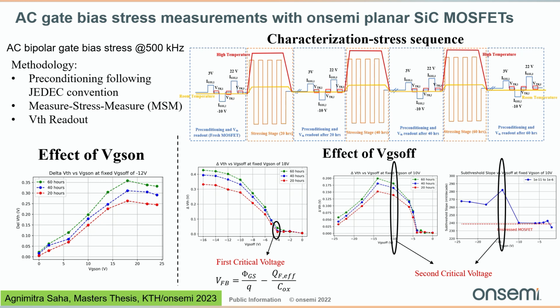And here Agnimitra looked into the dependence of different Vgs on voltages. So lower graph here to the left. Let's see if you can see. Anyway, with the minus 12 volt Vgs off negative, that gives quite much positive VTH shift. Then you can see that increasing the Vgs on, the shift is increasing, and after 18 volt, it's pretty stable. And you can see on the middle left graph that the Vgs off is the critical factor driving the VTH shift. So if you go down to about minus 4 volt, not much is happening.